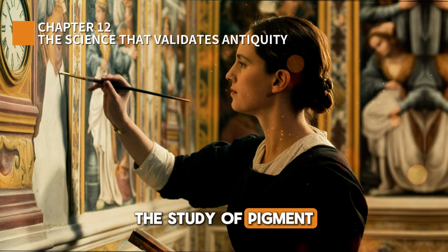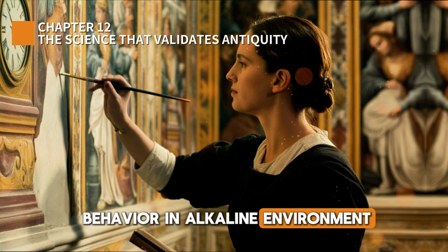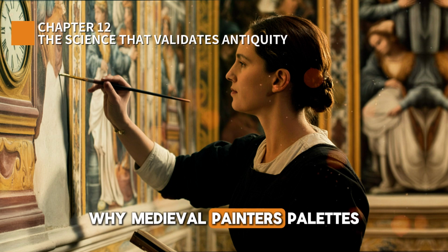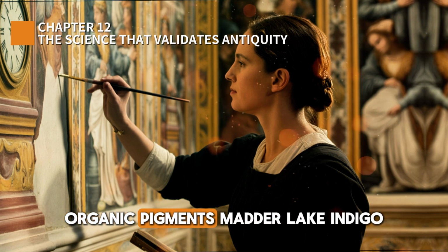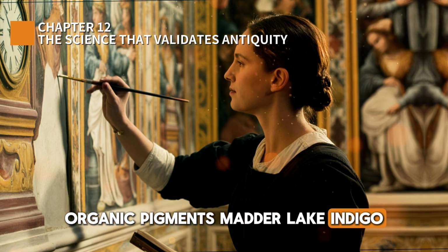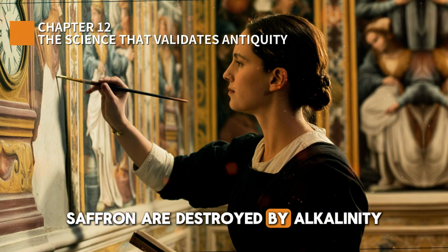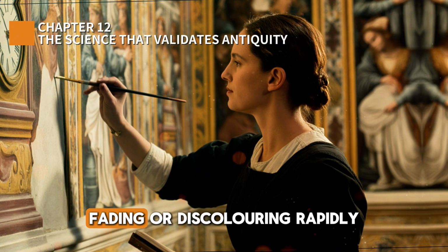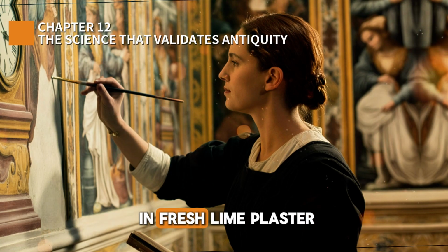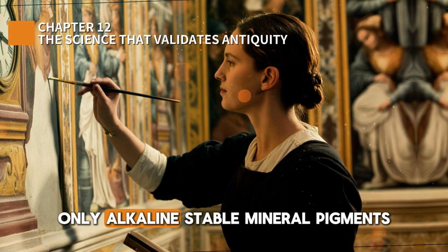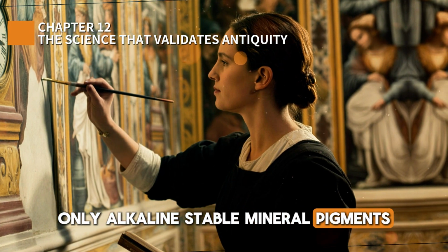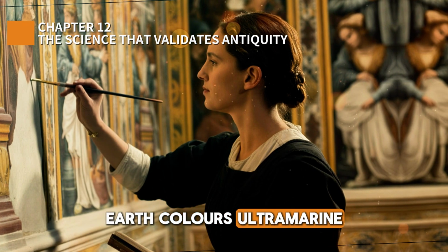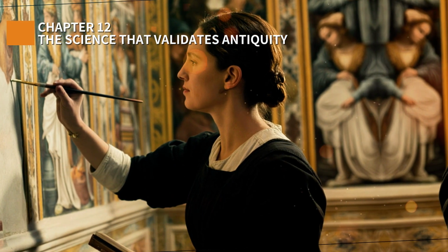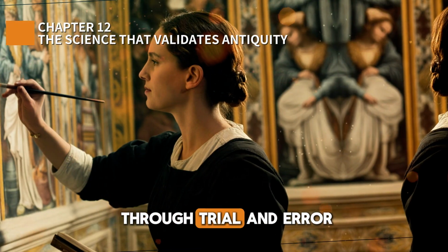The study of pigment behavior in alkaline environment revealed why medieval painters' palettes were limited. Organic pigments, madder lake, indigo, saffron, are destroyed by alkalinity, fading or discoloring rapidly in fresh lime plaster. Only alkaline-stable mineral pigments, earth colors, ultramarine, lead white, survive. Medieval painters learned this through trial and error, watching organic colors fail and mineral colors persist.